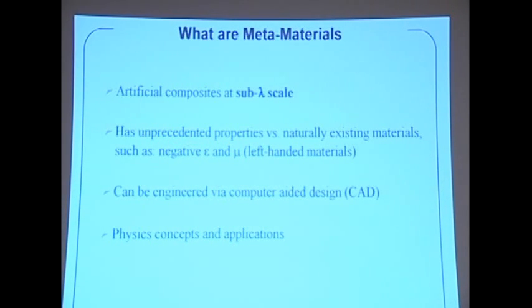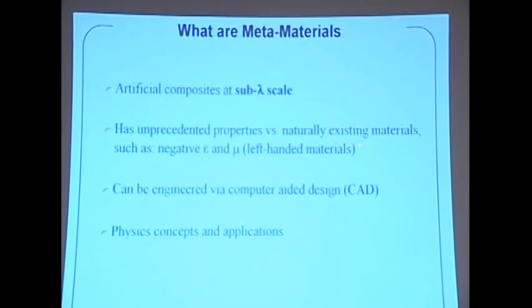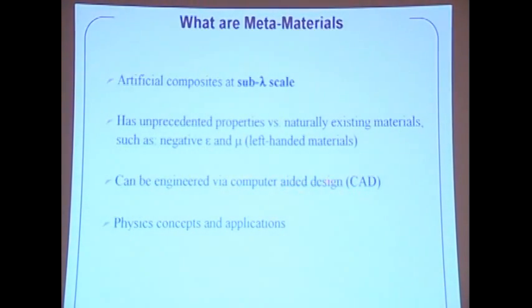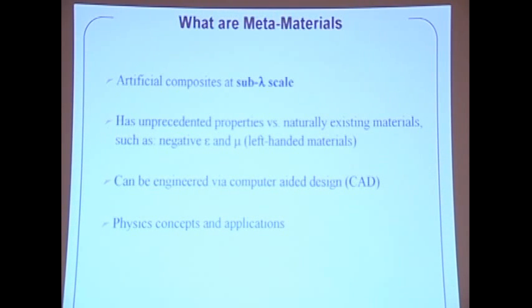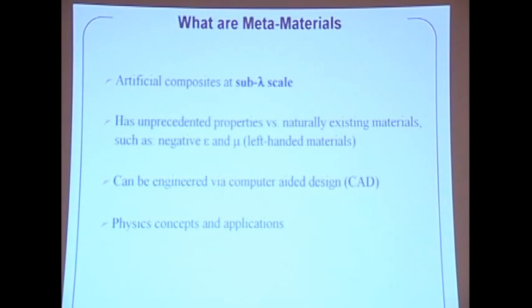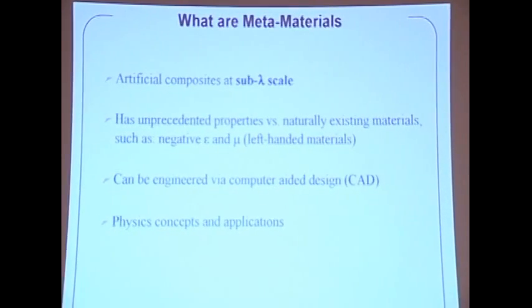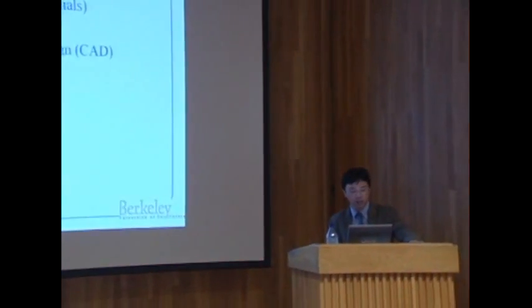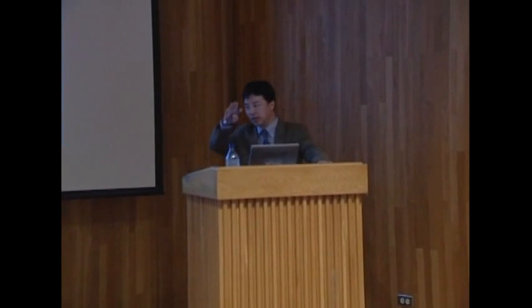Of course, we are looking at unprecedented physics or properties of those materials, which usually do not exist in natural materials. Third, because it is bigger, at least a few nanometers or micron size, you can use computer-aided design and a top-down manufacturing process, such as e-beam lithography or microlithography, so you can embed defects. Many of us know that for silicon devices, if you want to dope boron or phosphorus into the silicon wafer, you can pretty much control the concentration of the dopant inside the silicon crystal. But generally speaking, you cannot precisely define the position of a foreign atom such as boron inside the silicon crystal in the XY dimension. But here, because it is larger, you can use e-beam fabrication or something to engineer those defects or dislocations. Of course, we are looking at very exciting physics and applications.